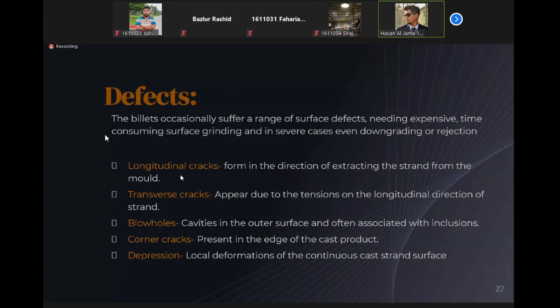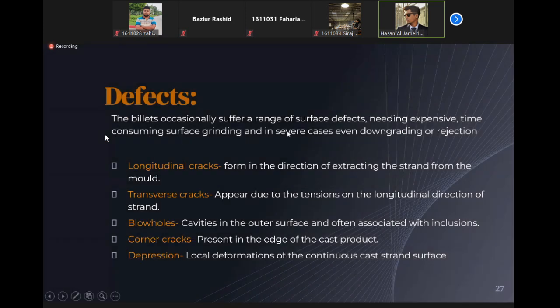So defects. The billets occasionally suffer a range of surface defects needing expensive and time-consuming surface grinding, and in several cases even downgrading or rejection. Some kinds of cracks are longitudinal cracks forming in the direction of extracting the strand from the mold, transverse cracks which appear due to the tensions in the longitudinal direction of the strand, blowholes in the cavities in the outer surface, often associated with inclusions, corner cracks present in the edge, and depression, which is local deformations on the continuous cast strand surface.